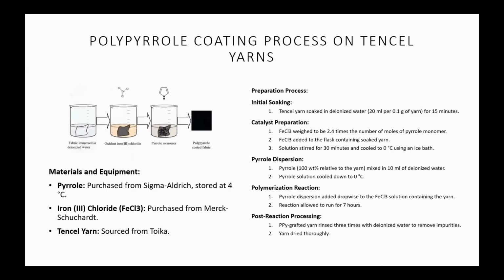So how do we coat a yarn with polypyrrole? First we need pyrrole, of course, and we need iron chloride. And in this case, we have used Tencel yarns. The first Tencel yarn is soaked in deionized water, and then iron chloride is added into the water, and then the pyrrole is mixed with deionized water and slowly dropped into this solution. The reaction happens for several hours. And in the end, we get this yarn, which is rinsed and dried.